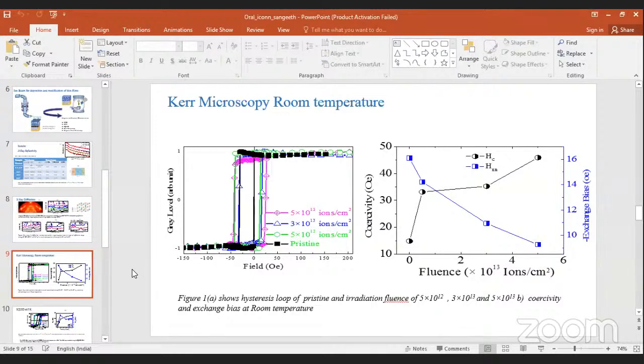From the figure we can see that the coercivity of the film has been enhanced, which means that the pinning centers present in the interface enhanced the coercivity. But here we can see that the exchange bias has been reduced. That means it is not normal in this case.